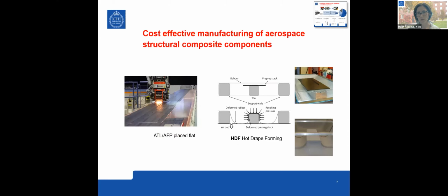The level of automation which we have been looking into for this particular case with the surface and the stiffeners is that we make a lot of layers, a multi-layer layup using an ATL or an AFP flatly. The outer surface can be made directly, of course, but we focus here on the spars. They can be laid up flatly and then afterwards formed in something called Hot Drape Forming, which is a process where you put your material as a stack.